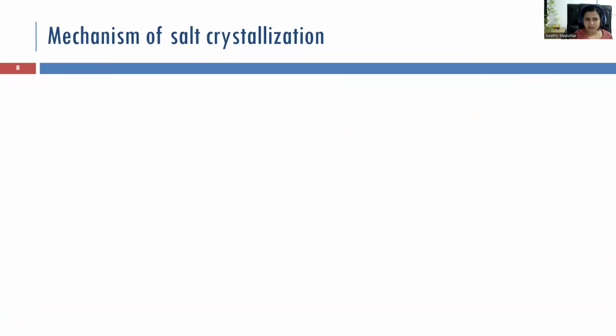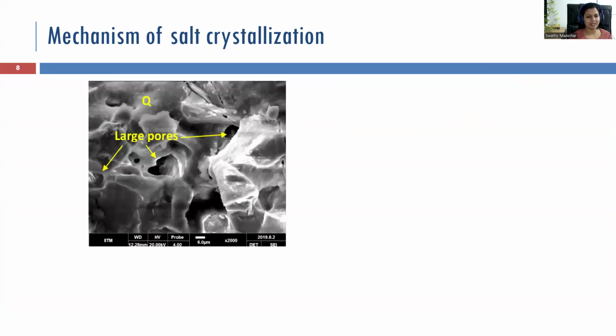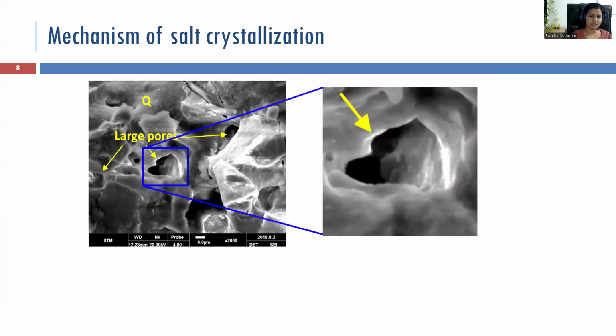What is the mechanism of salt crystallization? I'm going to show this based on one of the SEM images from one of the fired clay brick samples of mine, which was found to have larger round pores. So in large round pores, with subsequent dry-wet cycling, salt solution gets in and gets more and more concentrated or more saturated. When it reaches supersaturation, the crystal precipitates, and you see this is a large round pore.